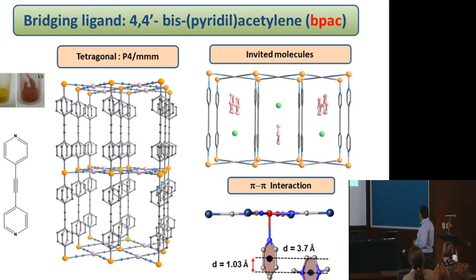Here we can see that using this BPAC, which is a bridging ligand of the three-dimensional structure, this molecule also enters the cavity of these large cavity complexes, okay? And thanks to pi-pi interaction between the aromatic cycle of the bridging ligand and the aromatic cycle of the guest ligand, okay? And we will see that the quantity of included BPAC molecule will be very important for the spin crossover properties. There will be a correlation between the quantity and the spin crossover properties.